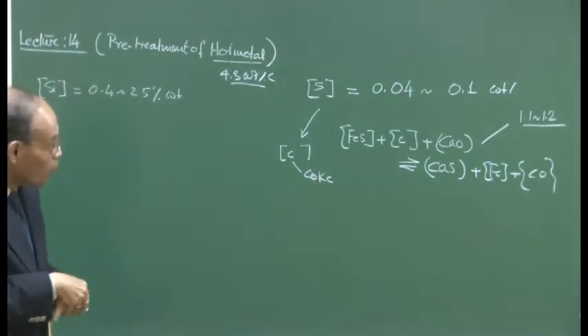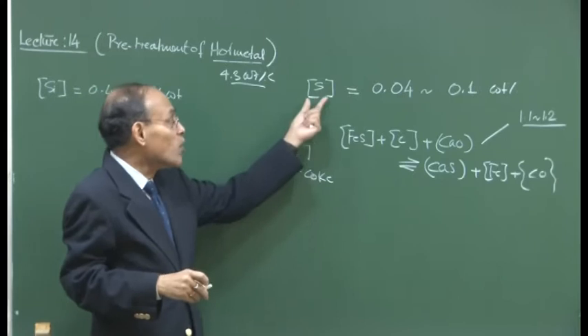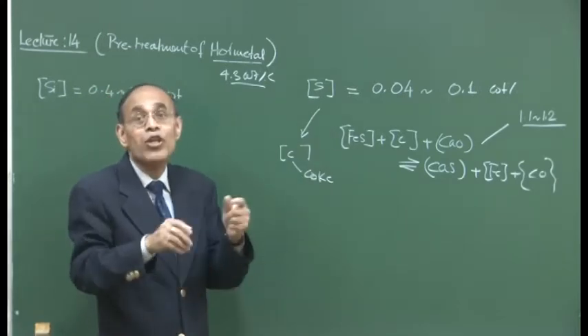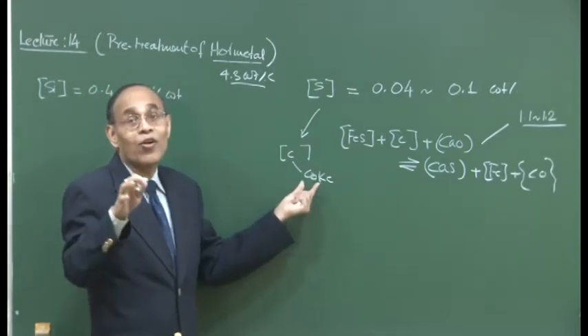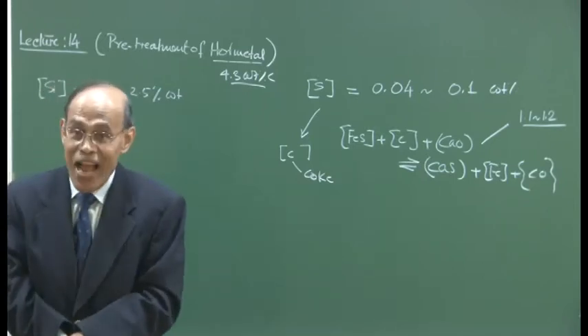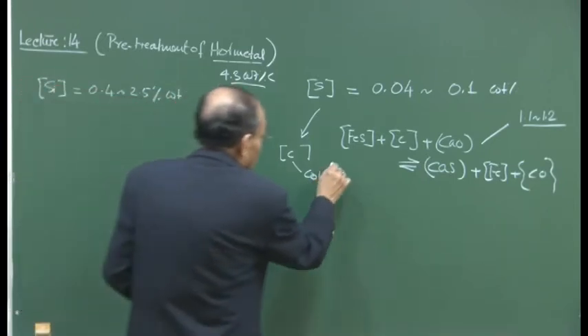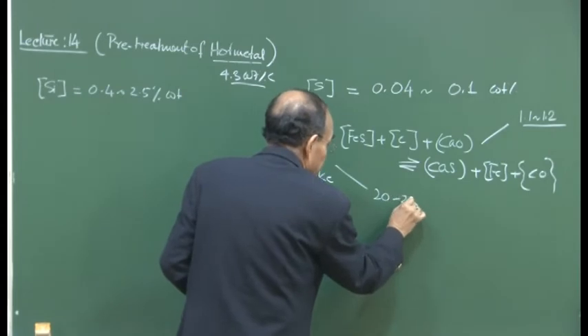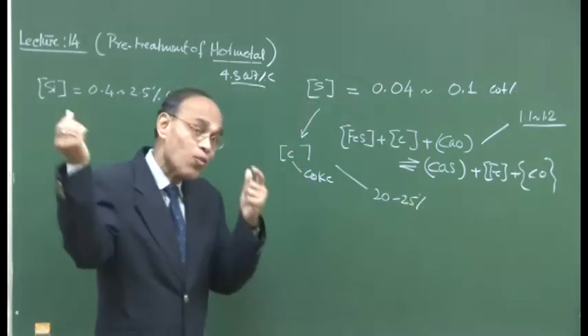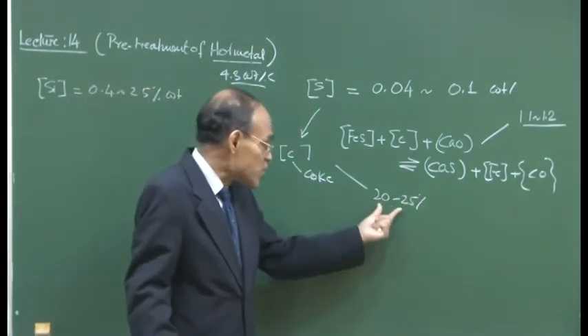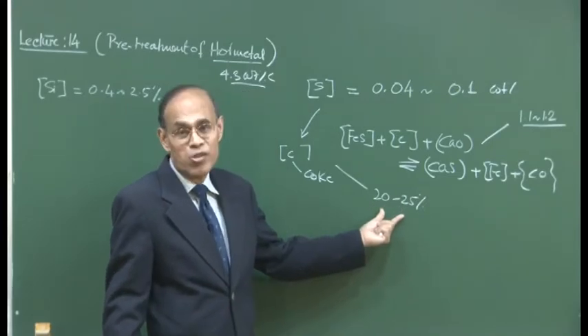Indian coke unfortunately contains much smaller amount of sulfur than the foreign cokes, but the Indian coke is known to be containing an enormous amount of coke ash. So, our coke ash can go to 20-25%. On the other hand, high quality imported coke can have ash content of the order of 7%, 8% or so.